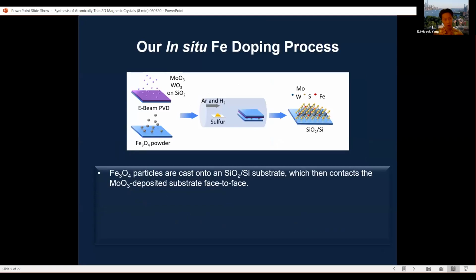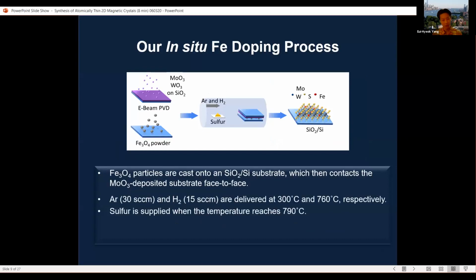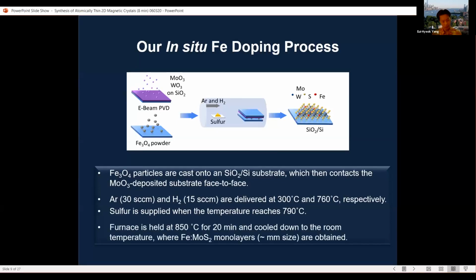In order to dope irons into this crystal, we use iron oxide particles cast onto the substrate, which then contacts another substrate face to face with the molybdenum oxide deposited. This is the transition metal oxide, which will be converted into molybdenum disulfide. With the right temperature, right time, right carrier gases and chalcogen powders, we hold the furnace at the right temperature and time before it is cooled down to room temperature, where iron doped molybdenum sulfide monolayers are obtained, and we make these up to a millimeter in size, which is significant in this area.